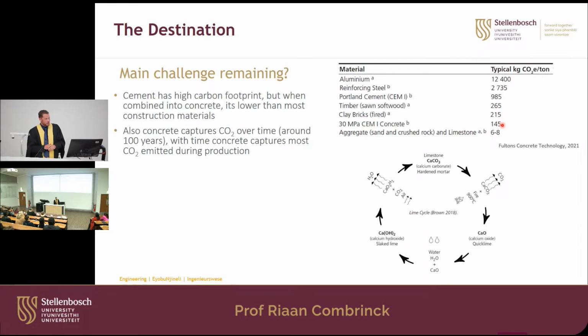So another thing about concrete that you need to keep in mind is concrete actually absorbs the CO2 with time. So it gets rid of the problem it created in the first place. It takes about 100 years, and that's the problem. But with time, this is the carbonation or the lime cycle: if you take limestone and you heat it up, the CO2 is given off, and then that calcium oxide, which is our cement basically, with water goes into calcium hydroxide, and with CO2 from the air, forms calcium carbonate again. So it reabsorbs that CO2. It just takes some time.